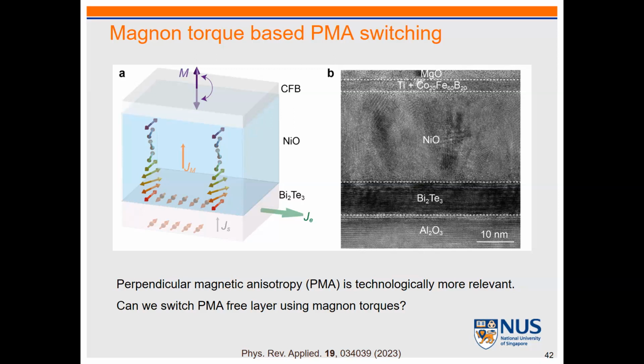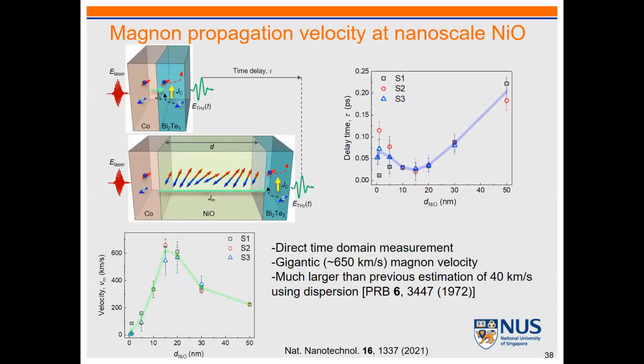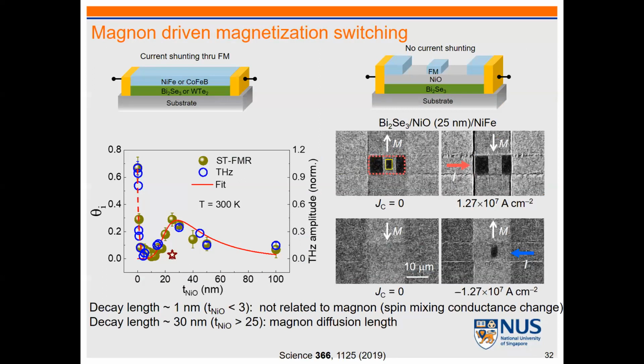And what is the magnon propagation length? I think it's a good question. So we try to extract it, for example, using this chart. There is a first decay. So once you use the exponential fitting, your magnon decay length is about 1 nanometer. And as I mentioned, this has nothing to do with the magnon, just because you need a few monolayers to make a long-range order. Any magnetic material, you need certain monolayers to make a magnetic order. So within this 1 nanometer, there is no way this is a magnetic material. In this range, this nickel oxide is non-magnetic. It's some kind of very dirty insulator.